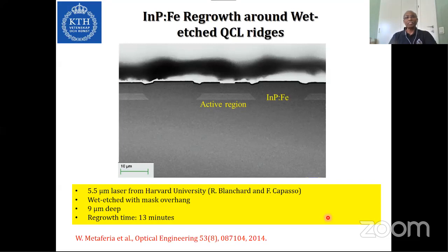So these are some examples of the structures which we have regrown. Very, very clean. This is the active region, and you see this is the indium phosphide, iron-doped indium phosphide. And this is a 5.5 micrometer laser, which was provided by Professor Capasso, one of the inventors of QCL. And we could grow in a very, very short time. Regrowth time is only 13 minutes. If you have to do this in MOVPE, it might take hours. So you see the beauty of this technique. That is why we are using it where it is strong.